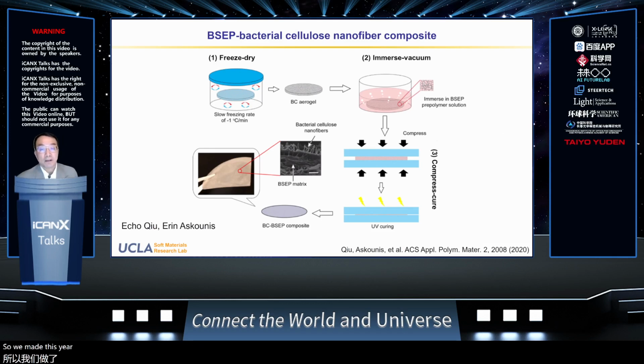So we made this composite, where we used the bacterial cellulose nanofiber as a filler added into the BSEP. The BC nanofiber swells in water. If you prepare a water swollen cake of this BC nanofiber, and then freeze dry it, you will have a BC aerogel. So you place that aerogel into this BSEP resin, the liquid formulation, and the monomers will diffuse into the aerogel. Then we compress it to remove the excess